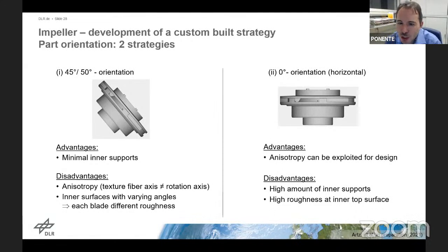That's better for the horizontal orientation. So there you would have 2 main axes in the texture or anisotropy of the part. One would be the build direction, vertical, and the direction in plane or orthogonal to that would have different mechanical properties in the material. So this orientation would be more suitable in terms of engineering using the mechanical properties. But it is more complicated in terms of internal supports because you will have all these flat downskin surfaces of this top plate that need to be supported. Otherwise, they will not be stable on top of the powder bed. So manufacturing-wise, this is the worst choice.